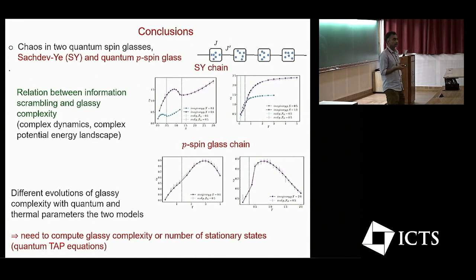In most of the cases that I have seen, the OTOC seems to saturate. It doesn't really diverge or anything. Are there systems where it actually does? No. In these systems also it saturates eventually. The field theory calculation that we are doing cannot capture the saturation part, so you only extract the growing part. The point is also that the saturation time in this model is infinite because of the large n limit, but it will saturate for finite n.